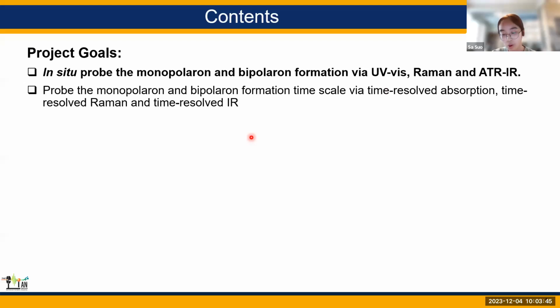I'll briefly introduce the goal of this project. So the first goal of this project is to achieve in situ probe of the monopolaron and bipolaron formation with different spectroscopic techniques. For example, UV-Vis and also vibrational techniques such as Raman and ATR-IR. And once this goal can be fully achieved, we understand all the information, then we can further extend this to time resolved study. So we can probe the evolution of monopolaron and bipolaron formation via time resolved absorption and also time resolved Raman and IR.